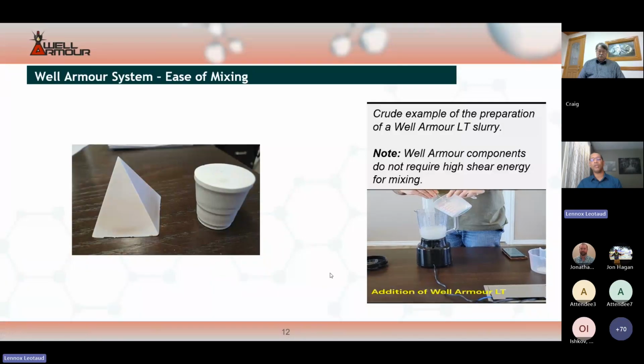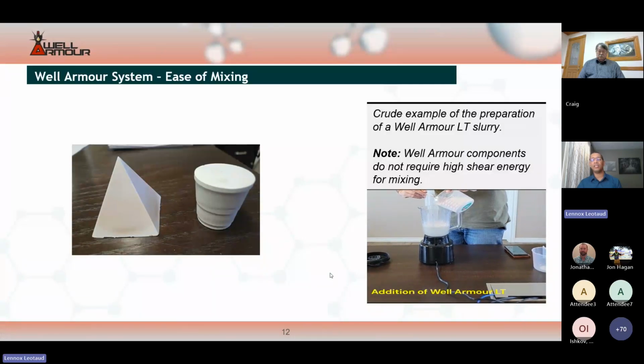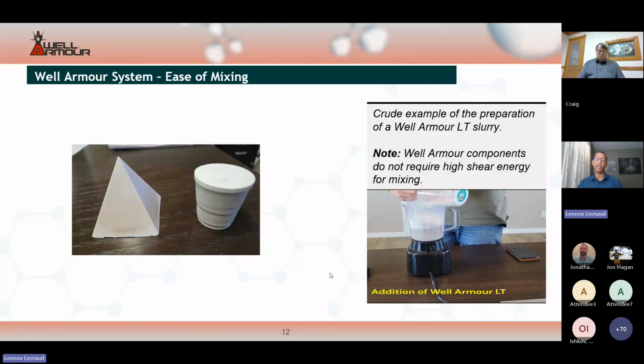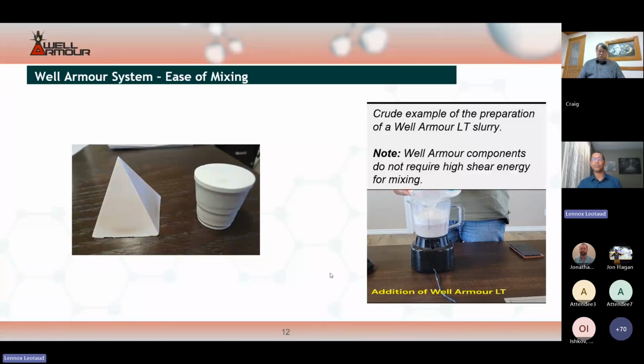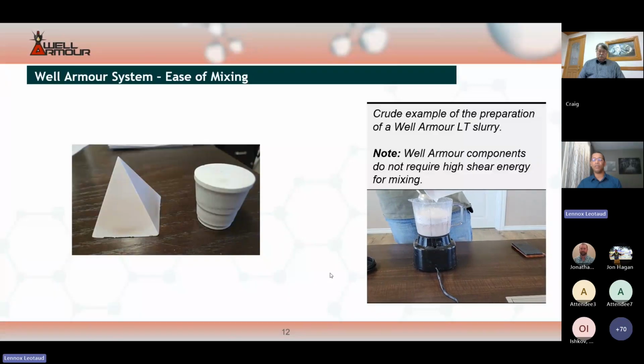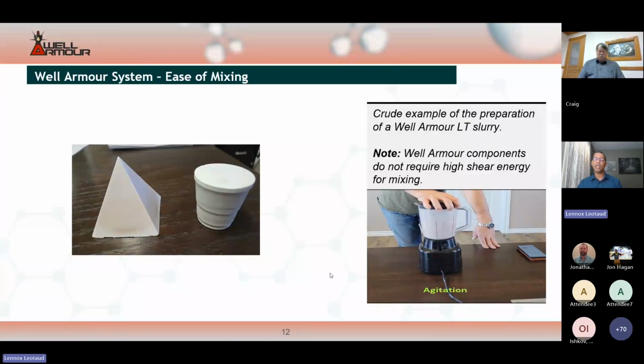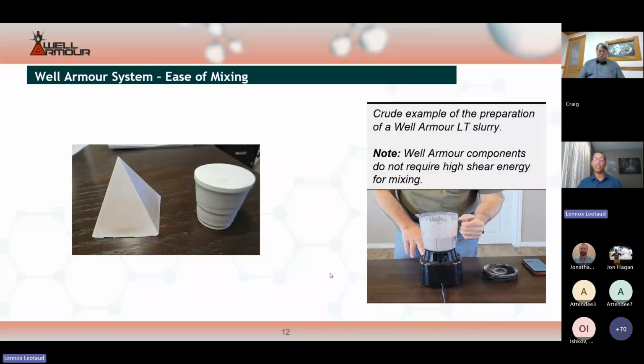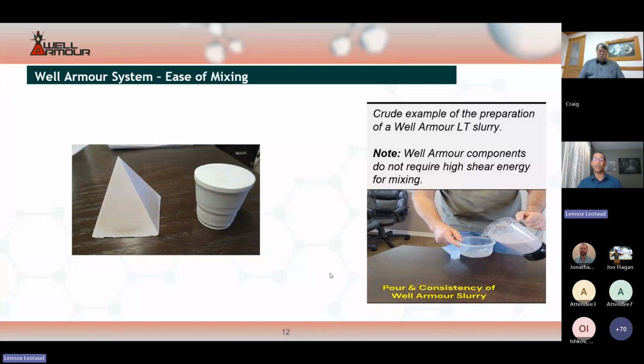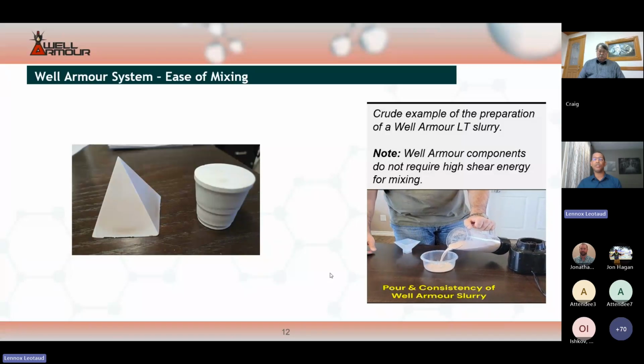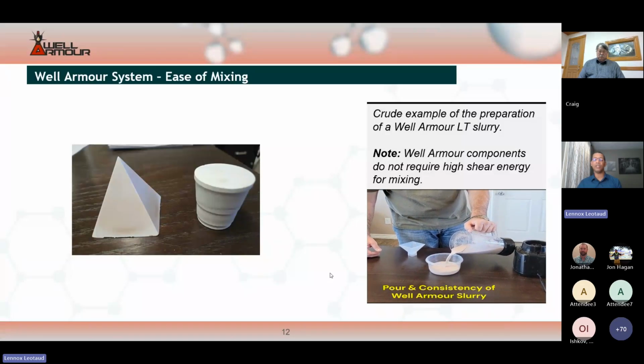the Well Armour components do not require high shear energy for proper mixing. The Well Armour slurry can be mixed in any standard oil well cement mixing equipment. The Well Armour material, when sent to a well site, will generally be provided in 50-pound bags on a pallet. And so to avoid having to lift the 50-pound bags or use a forklift to lift the pallet up, say, to the mixing platform of a cement unit, if a jet mixer is available, it can be used to add the sack material to the jet mixer at the ground level. So for large volume jobs, the preference is to mix the Well Armour slurry on the fly.